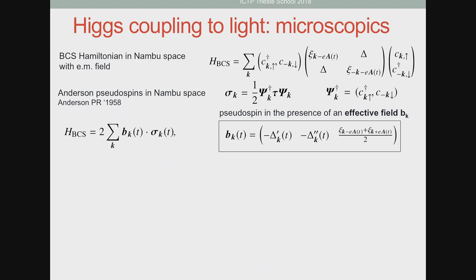And this effective field is a three-component vector. The first two components are essentially the imaginary and real part of the superconducting gap. So if you take, for example, the superconducting gap would be real, one of them would be zero. And the third component will include the dispersion. And if you introduce the coupling between light and the superconductor using the Peierls substitution, this will be the sum of xi k minus eA plus xi k plus eA.